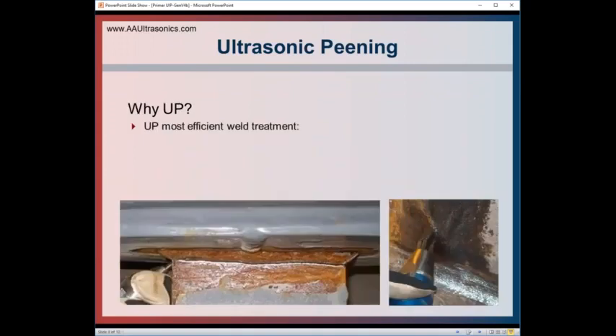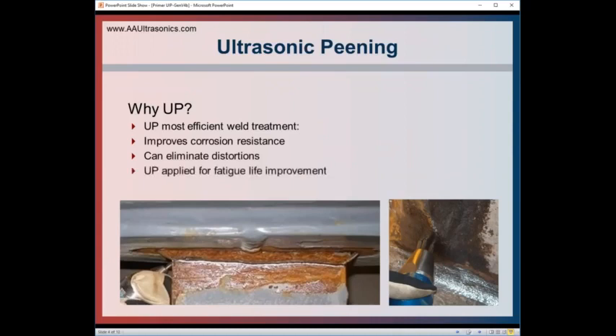Fatigue testing of welds treated by ultrasonic peening shows it's the most efficient post-weld treatment compared to traditional techniques such as grinding, TIG dressing, heat treatment, pneumatic hammer peening, and application of low transformation temperature alloys. It improves corrosion resistance of welded elements and treated surfaces. It can eliminate distortions from welding and other heat or bending processes. Ultrasonic peening may be applied for fatigue life improvement during manufacturing or repair of welds.